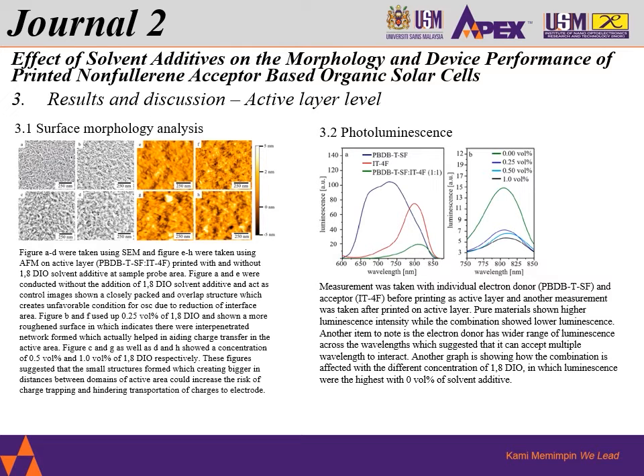So over here, these photos are with the 0% DIO concentration, and then 0.25%, 0.5%, and 1%. At 0% concentration, you can see that the structure is more closely packed and overlapping. This actually creates an unfavorable condition for OSC due to the reduction of interface area.